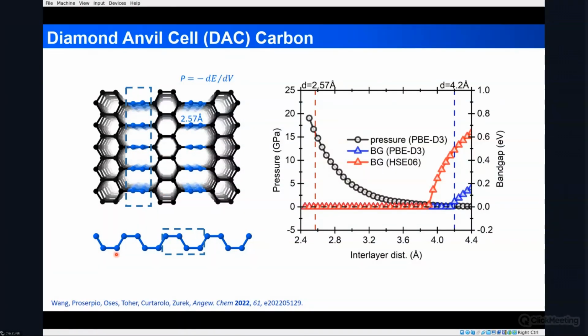And it can be thought of as these types of polyacetylene-type chains that are held together by this sp3 carbon network, and that is imparting a pressure on this system. So this is the reason why we call it diamond anvil cell carbon, because of this artificial pressure. These would prefer to be around 4 angstroms apart from one another in the solid state, but because of these black carbon atoms, they are actually constrained to be about 2.57 angstroms close to one another. And we can estimate what the pressure imparted by this lattice is.